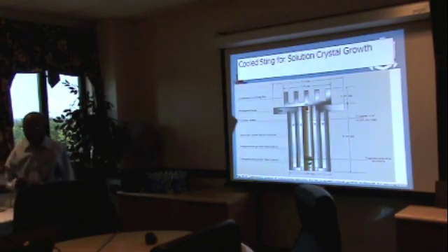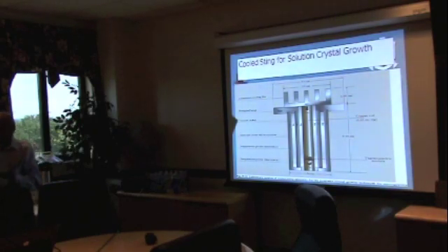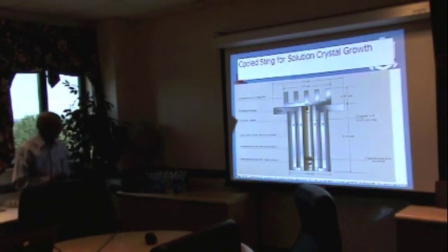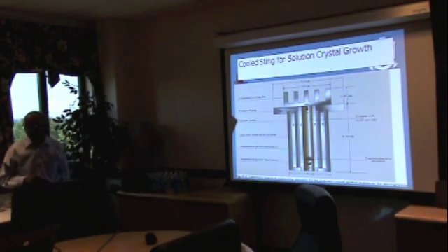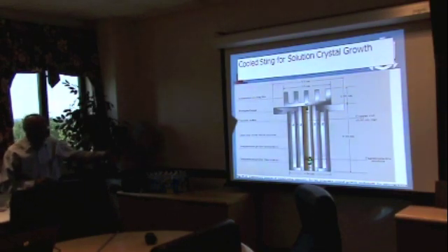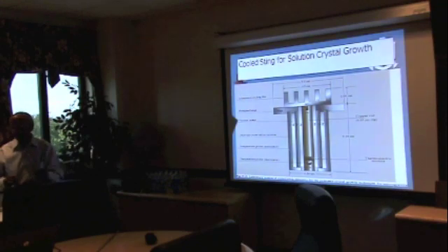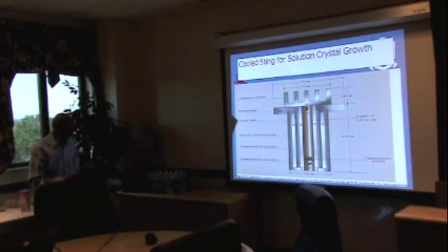And the reason for making this hot is that in solution growth, anytime you grow a crystal, you need to dissolve the seed crystal before you start growing. The reason is that there are always some defects on the surface. Even a natural surface might have some particles on it or something stuck, although we do all the work in a clean room. So before we start the growth, we heat the seed crystal so that a few microns of the surface are dissolved. And then we change from the dissolving to the cooling side, and then the crystal starts growing. So then we change the direction of the current.